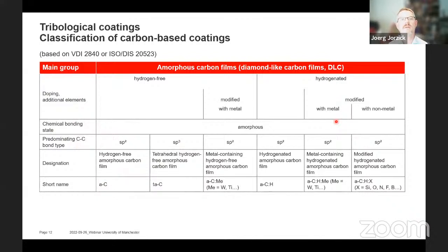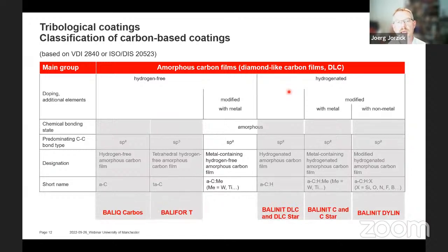Starting with the family of the carbon-based coatings, we can distinguish between the hydrogen-free and the hydrogenated carbon-based coatings. And here's a small excerpt from what Oerlikon is offering with brand names like BALIQ Carbos, BALIFOR T, which is a ta-C, and I will show you an example about this later, and the DLC Star, which is a hydrogenated a-C, which is widely used also for a lot of applications.